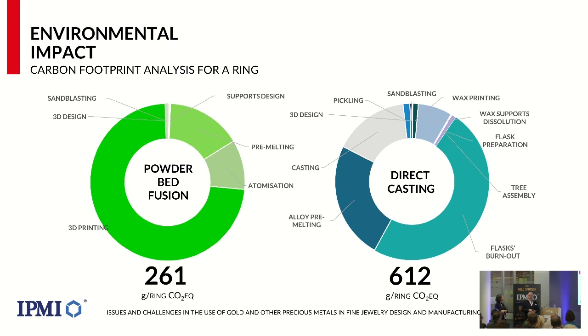So here we have an example of a paper that we presented already 6 years ago at the Santa Fe Symposium, doing a calculation and comparing direct casting with powder bed fusion, also called selective laser melting or direct metal laser sintering. For a single ring of platinum 950, the additive manufacturing, so the powder bed fusion, was producing 261 grams of CO2 compared to over 600 grams. And this didn't count all the energy or the environmental impact to dispose of the investment.